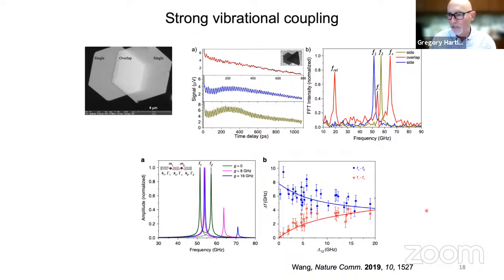There's coupling between the 2 vibrations that causes a shift in the frequencies when the 2 plates are overlapped with each other. If we use this data to work out a coupling constant, we get about 8 gigahertz, which is really very strong coupling, because the frequencies are less than about 80 gigahertz in these experiments. So the coupling between them is over 10% of the actual frequency. These are very strongly coupled systems, so that's sort of interesting. And it's an example of a classical mechanics example of a strongly coupled 2-level system.